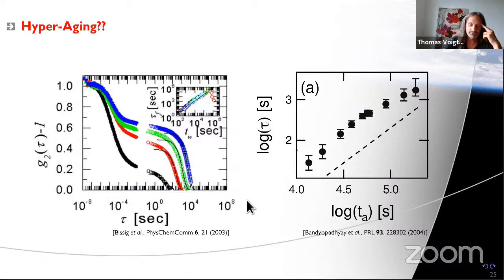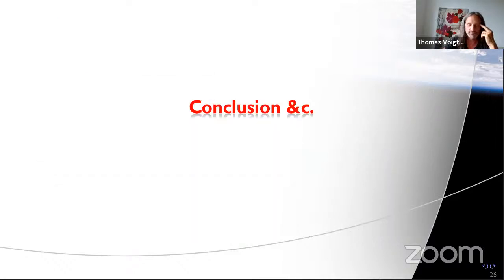Interestingly enough, and Stefan might be the better expert on this, people have seen this or claimed to have seen this in physical gels. You have to look very closely. Check the papers, but this is a figure from the paper already blown up 5 times. And then you have to look into the inside and you have to see that this line here is not a linear relation between tau and TW, but superlinear. So at this point, I think you just have to believe the authors or me. Same here, but there are some indications of hyperaging. So this grows faster than the waiting time, and then it levels off again. This is not unlike what we're seeing in our theory.